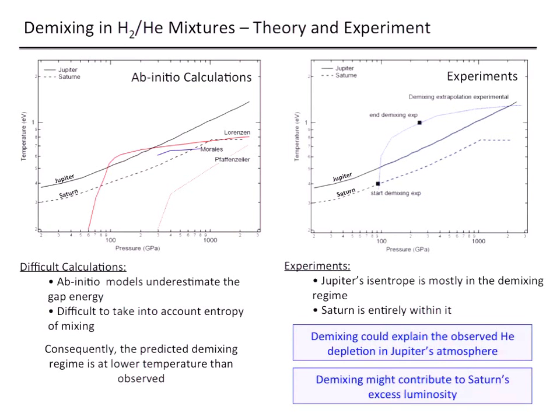We can put limits on where this demixing is occurring relative to the planetary isentropes and compare to predictions. What we see is that the ab initio models are probably underestimating the gap energy, because they're predicting that these materials become metallic sooner than they do. It turns out that the insulator-metal transition is probably what's dictating the solubility.